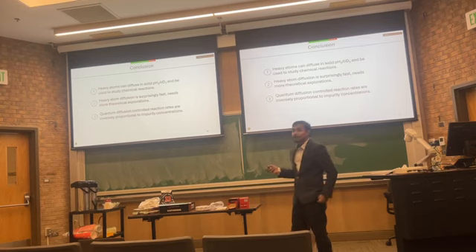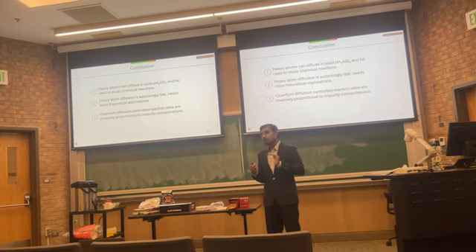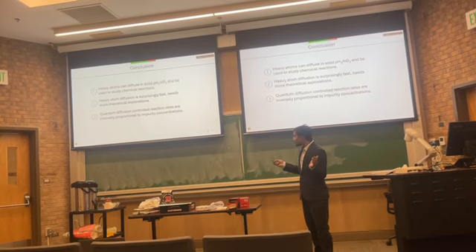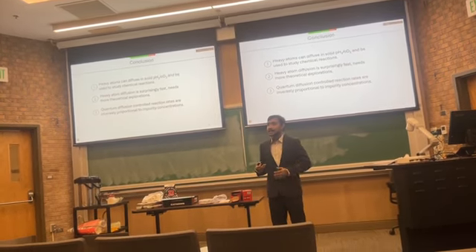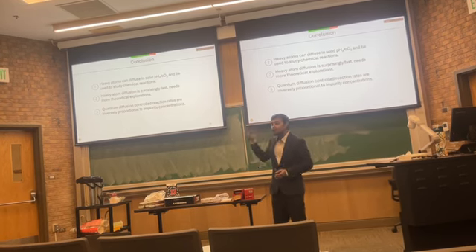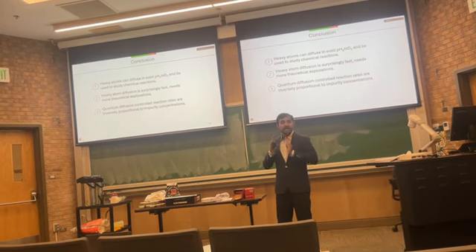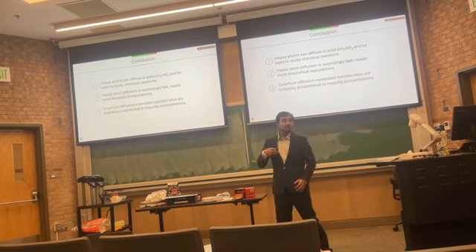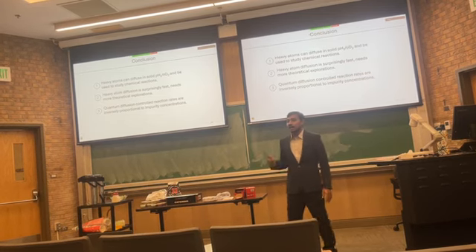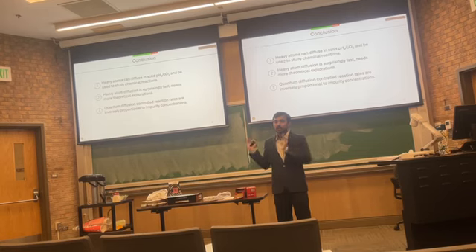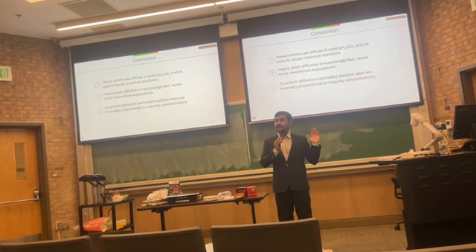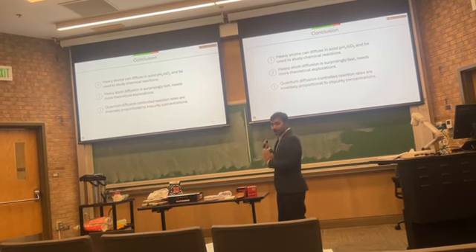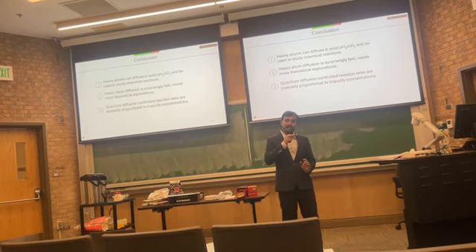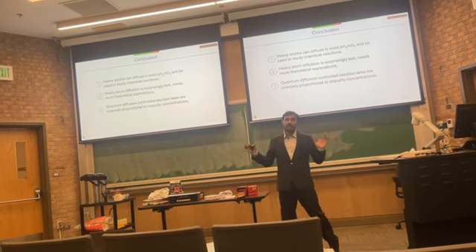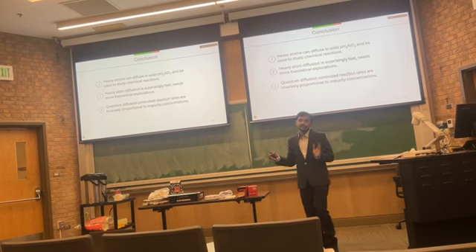And also, we have found that our diffusion coefficients or rate constants are inversely proportional to the impurity concentration. So what I'm proposing in my thesis is that, as we have seen this in all my projects, in every project we saw that inverse relation. So whenever you report a diffusion coefficient by quantum tunneling or a reaction rate by quantum tunneling at this low temperature, you should report the temperature, and you should also report the dopant concentration or impurity concentration of the system.